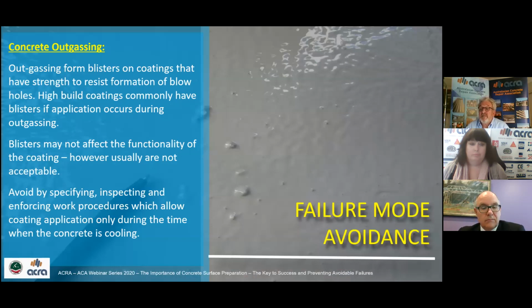Outgassing. Outgassing forms blisters almost instantly on applied coatings that have had sufficient strength to resist the formation of blowholes. Heavy build coatings commonly will have blisters if the application occurs during outgassing. Depending on the conditions of use, the blisters may not affect the functionality of the coating. However, blisters usually are not acceptable. You can avoid this by specifying, inspecting, and enforcing work procedures which allow coating application only during the time when the slab is cooling, falling.